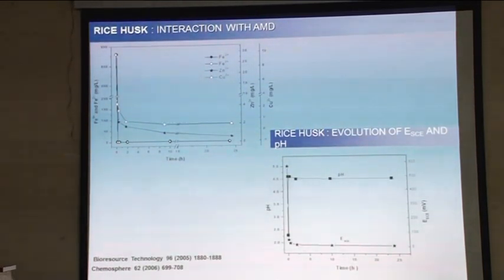And then if you correspondingly see the changes with respect to pH and the redox potential, because I told you that the sulfate reducing bacteria is an anaerobic organism, that means it cannot grow in the presence of oxygen. You need reducing conditions. So we can see that the redox potential is also significantly reduced when you take the extract from the rice husk, and then you see that the pH, which was initially 2.3, is now raised to about 4.5.